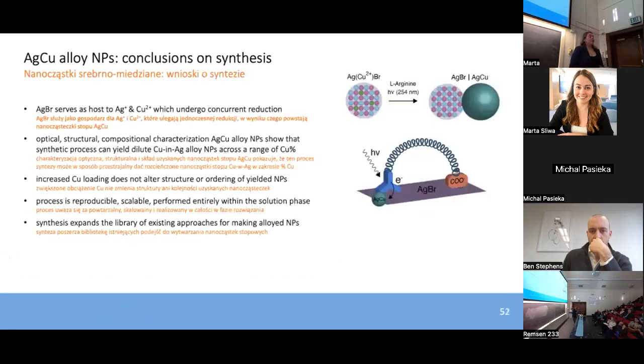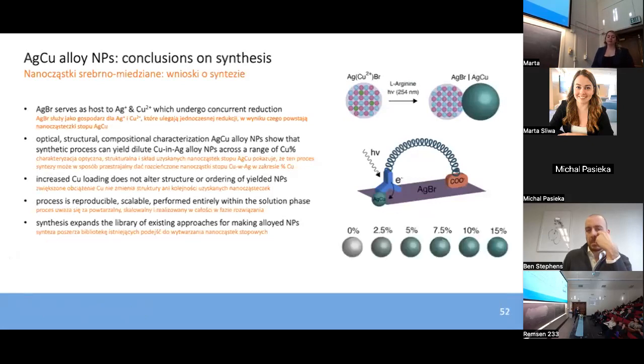So to recap what was presented in this last section, or that expansion of the host-guest technique to other materials, we were able to form silver copper bromide host nanoparticles, and from them derive silver bromide silver copper alloy nanoparticles. The copper interstitial cations hosted within that silver bromide host lattice undergo concurrent reduction in the presence of L-arginine and UV light to form that secondary phase. We can isolate that secondary phase and also tune the amount of copper that we introduce in the solution to get copper and silver alloys with percent copper across this range of nominal loading.